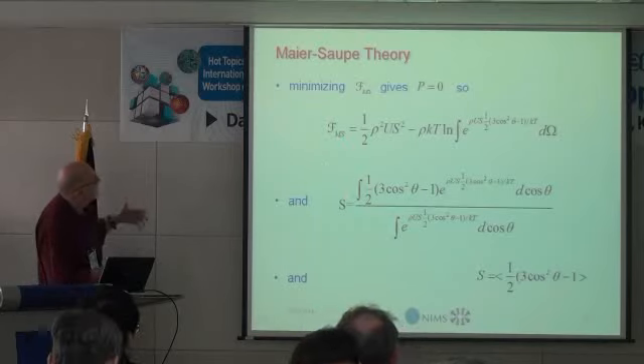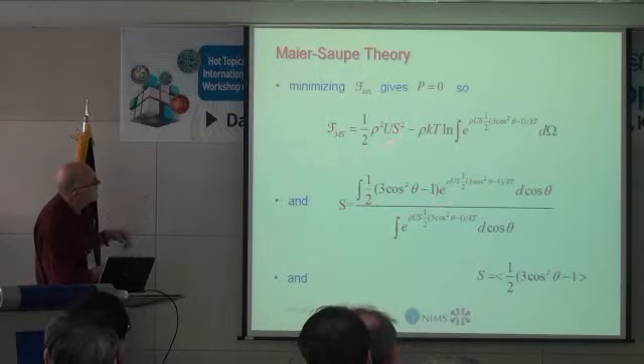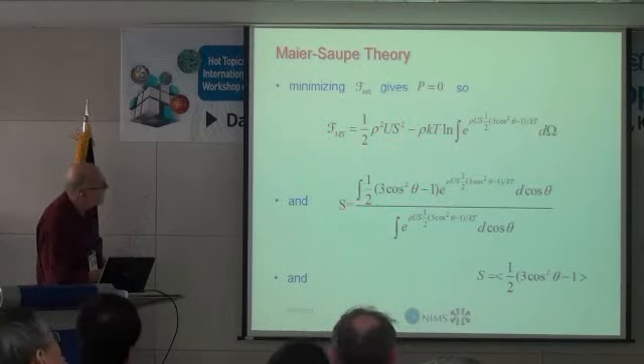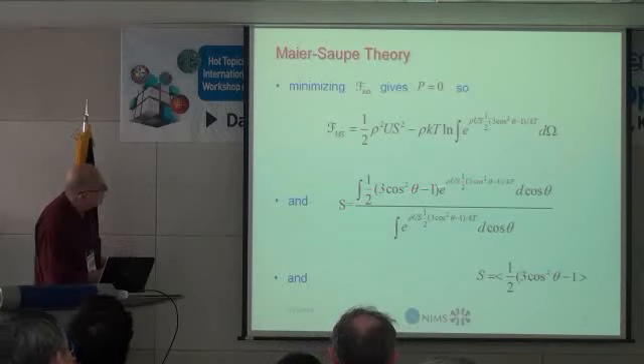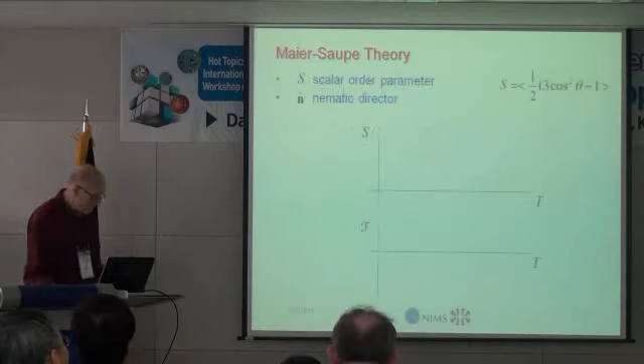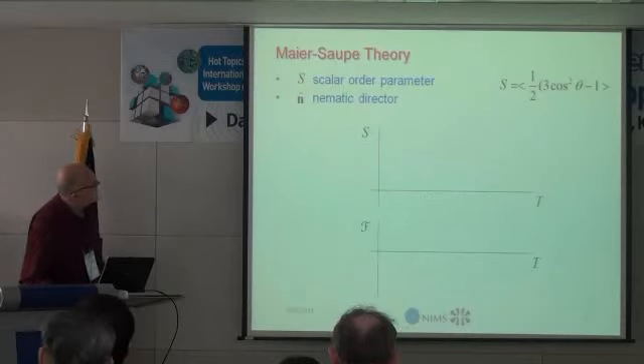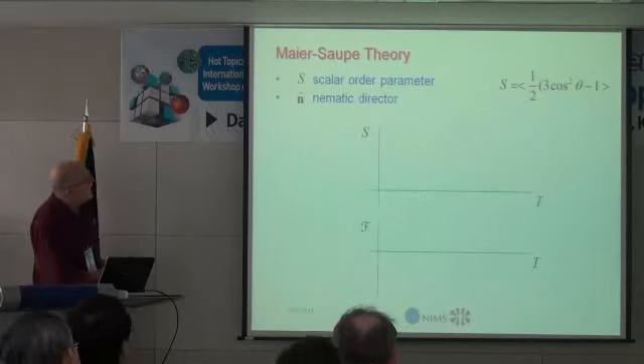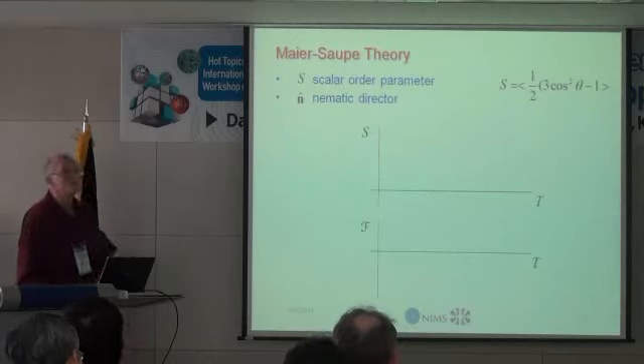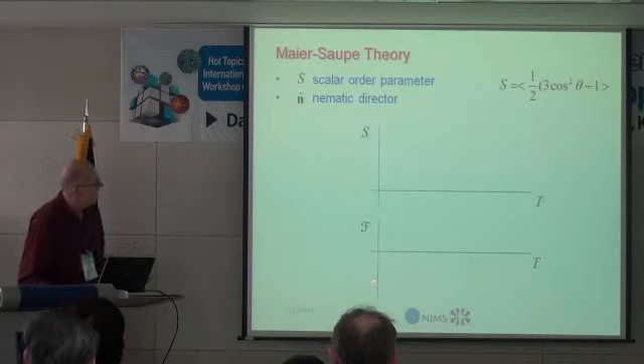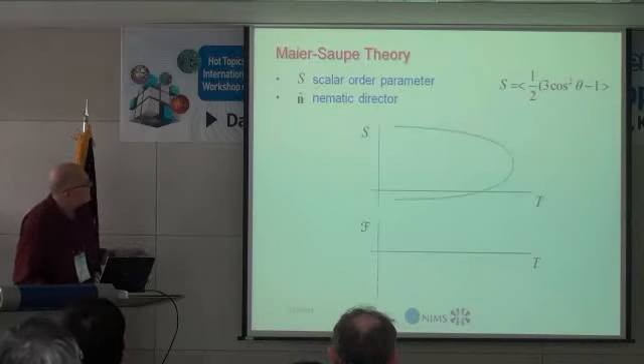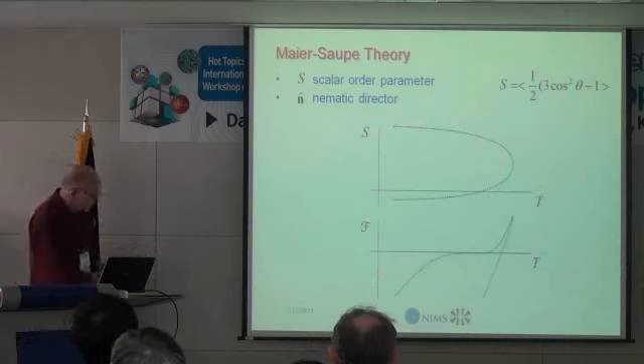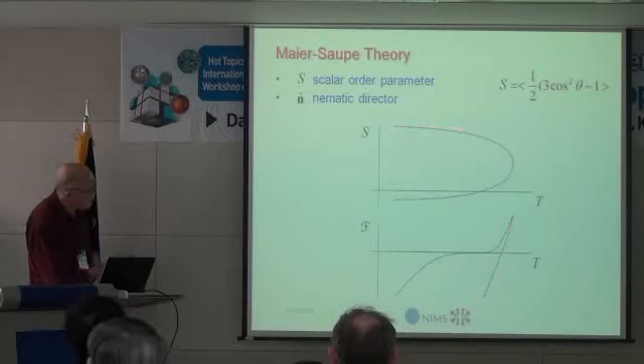So one gets, writing things in terms of the scalar order parameter, it looks like this, and one gets a self-consistent equation for S. Basically, this is just the second Legendre polynomial, and S appears here as well as here. So, when you do all this, what does it look like? Well, it turns out that there are two solutions. So S equals 0 is always a solution. So the disordered phase is always a solution. Free energy is 0. The other more interesting solution looks like this. And this is the corresponding free energy. So this branch corresponds to this branch up here.